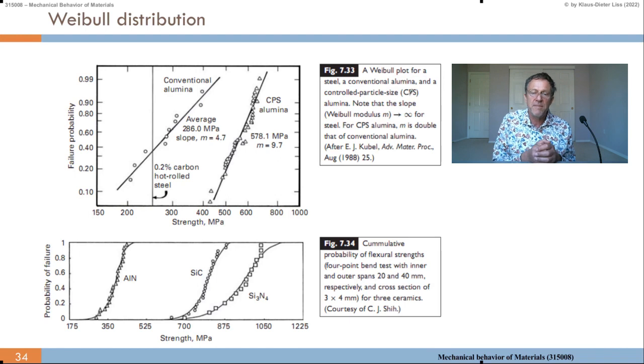Alumina, you know, it's a polycrystalline material. It's made by crystallites. They are sintered together, or they're ground together. And if you have a controlled particle size distribution, let's say all the same, then you have better statistics in failure. So a higher M, 9.7 here, as compared to just a very dispersed particle size with a broad distribution. Because if you have a broad distribution of particle size, you also have a broad distribution of flaws and imperfections. So this is a nice example how you can design the Weibull modulus M by controlling the microstructure of the material.